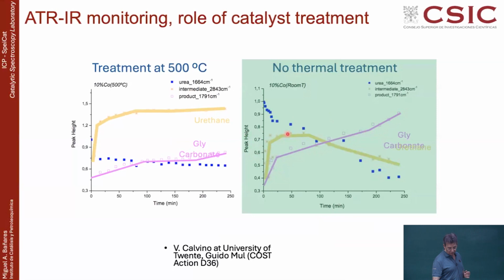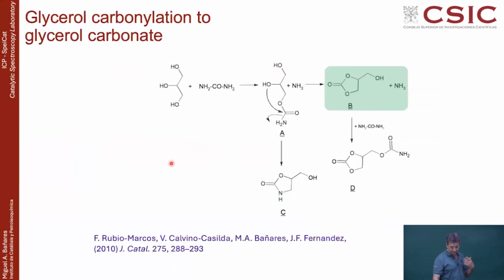There is another product which is in between, the urethane. The urethane is when you make the carbonate, only one is connected. So this is half a cycle. So that intermediate becomes the dominant in the temperature that was treated at high temperature. But in this case, that one is basically an intermediate and then ultimately goes to the final, much more efficiently than in the other one.